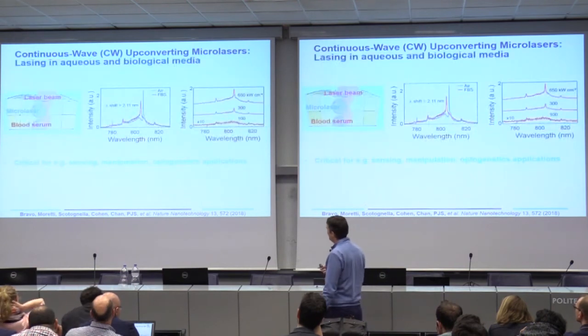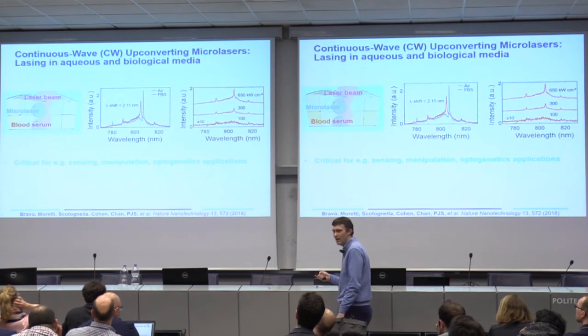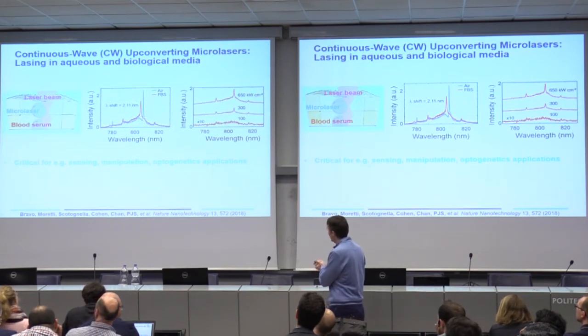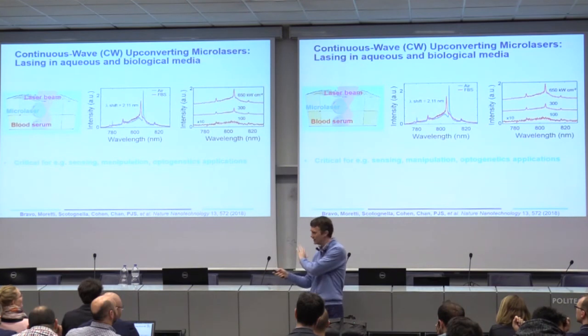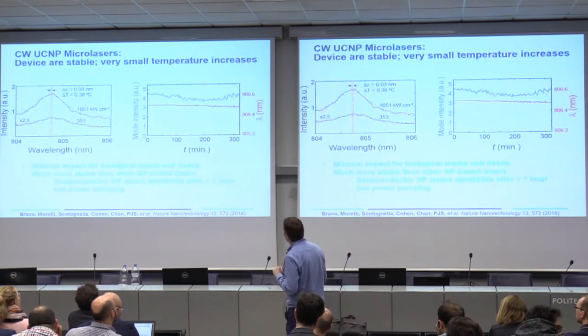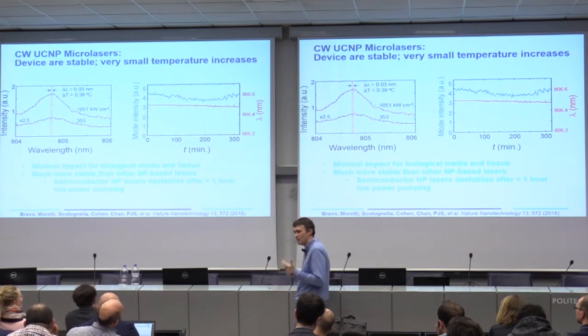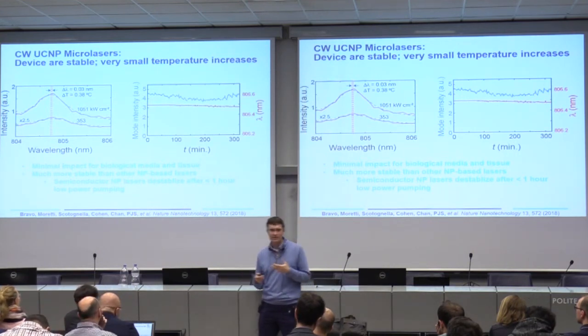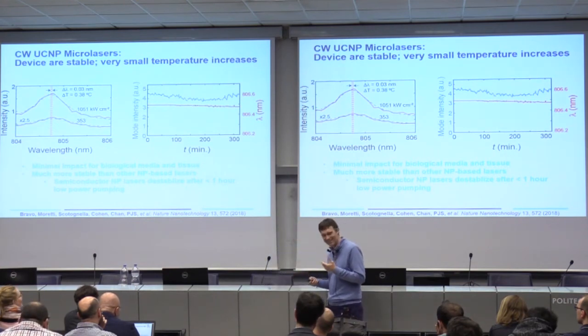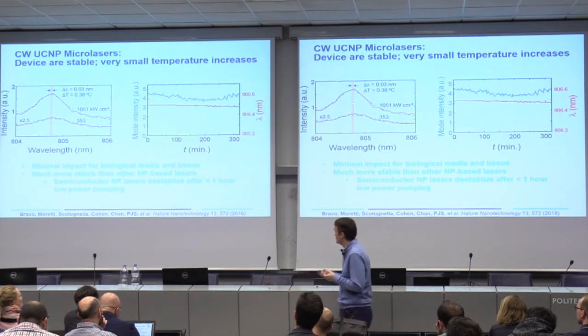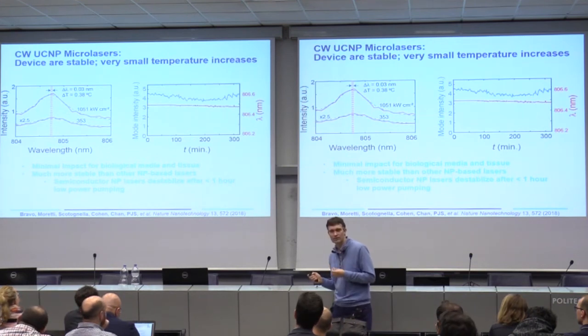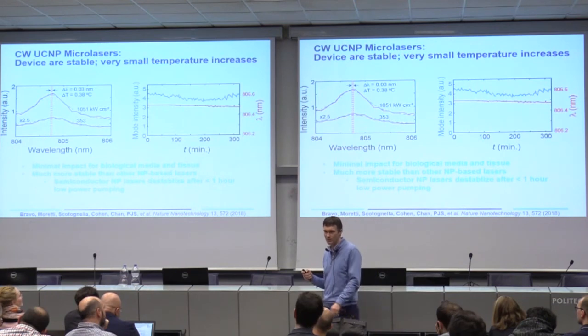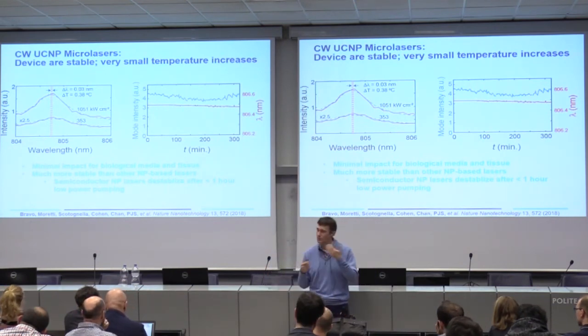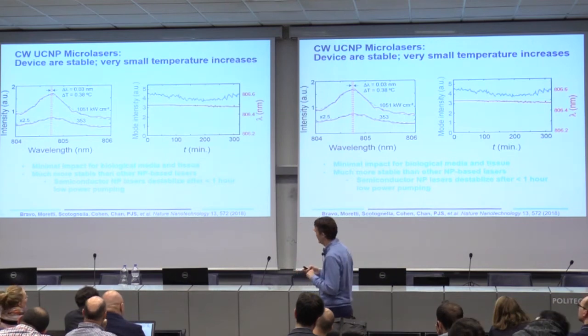So this got us pretty excited. It turns out that they still work if you put them inside of a biological material. We put them in blood serum, and you can see that, in fact, they still lase. This is also an initial demonstration of the sensitivity. Just by changing the local environment, the laser mode shifted around. So that may be good for something. They're also extremely stable. For as long as we shined our laser on them, they kept lasing. If there's anyone here who's familiar with nanoparticle lasers, that doesn't usually happen. Usually they eventually die. But these just keep going for as long as we'd pump on them. And the temperature increase was only about 0.4 degrees when we're pumping well above the threshold. So they don't heat up that much, which is also nice, and it gives you a signal that they're maybe somewhat efficient at doing this lasing.